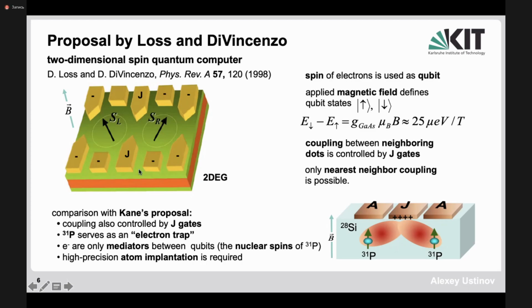However, here is a much, I would say, technically easier task because you don't need to implant spins of phosphorus, but you basically form the spin states on the surface of the two-dimensional electron gas. And this size here can be as large as, let's say, a few tens of nanometers or even 100 nanometers. And then in the Kane proposal, electrons were only mediating interaction with nuclei. Here, you don't need to mediate anything. You work directly with the spin states of electrons on the dots. So basically, it sounds simpler. And it turned out to be somewhat simpler.